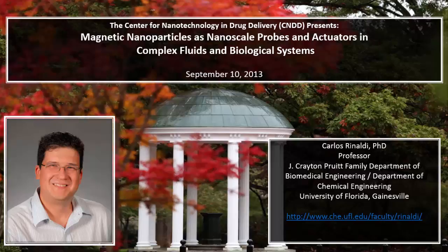I should have put this before: these particles are being made by the thermal decomposition method, and there are a variety of methods using acetylacetonates or pentacarbonyls. We use an iron oleate route. It results in hydrophobic oleic acid-coated particles, which are the ones that I used before, and we can make them with relatively narrow size distributions.